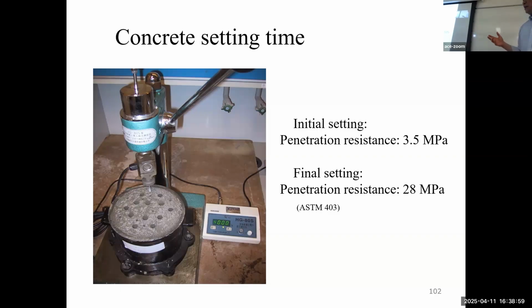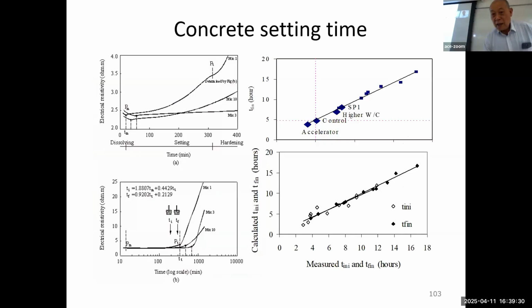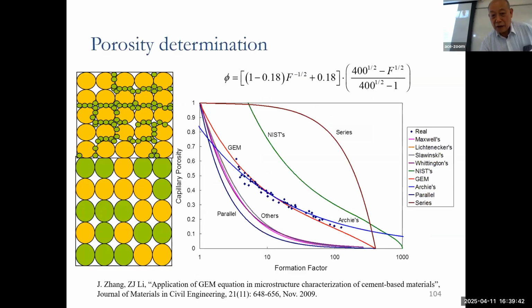Then the second PhD student did this. The main contribution of her work is that she utilized this non-contact resistivity to indicate the setting time for concrete, because measuring setting time for concrete is very difficult. You need to sieve out the coarse aggregate, make a mortar, and then do penetration tests, so it's very time consuming and labor intensive. However, by utilizing this non-contact method and the characteristic points, we can predict very well the initial and final setting time for concrete.